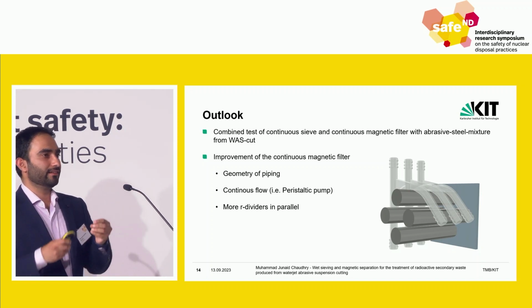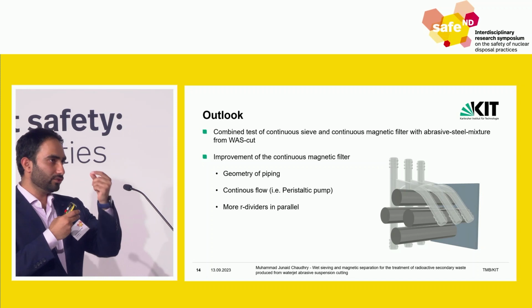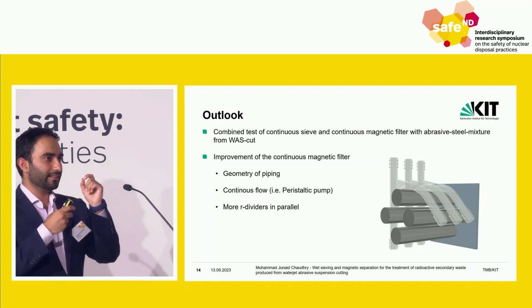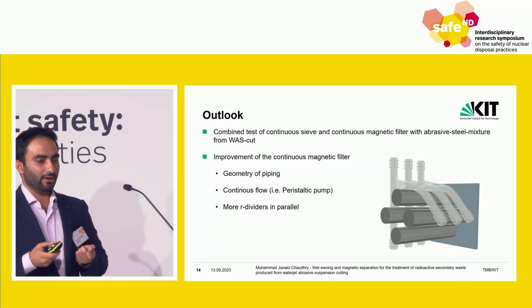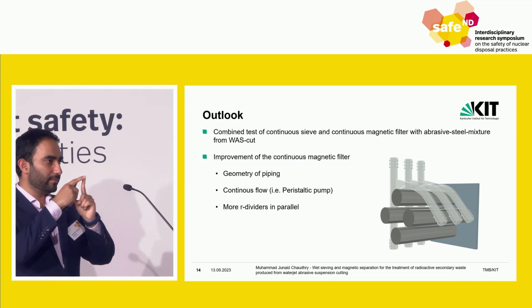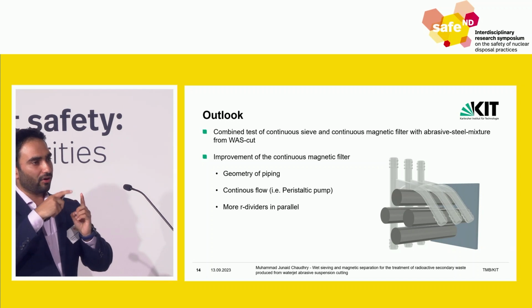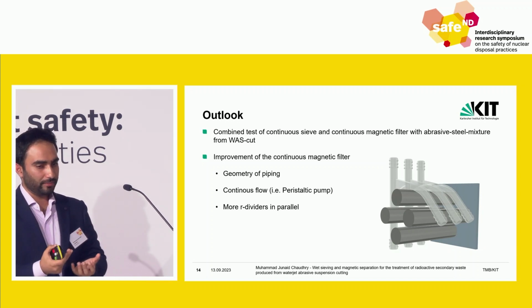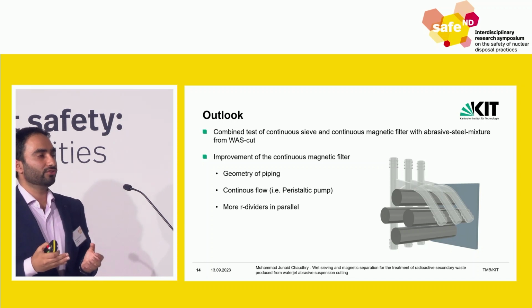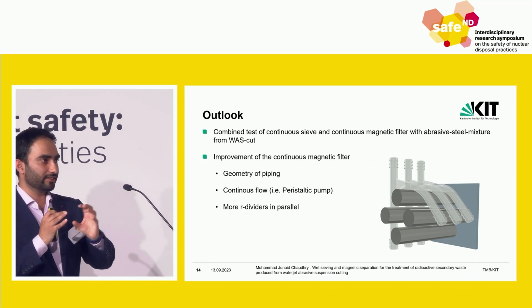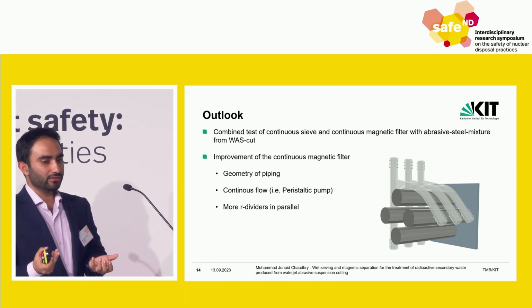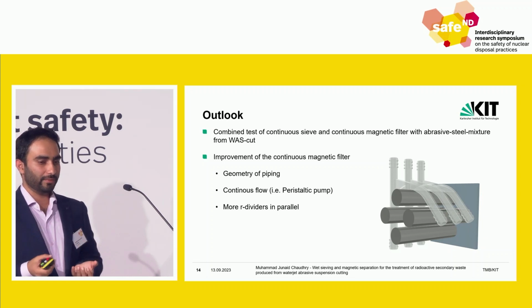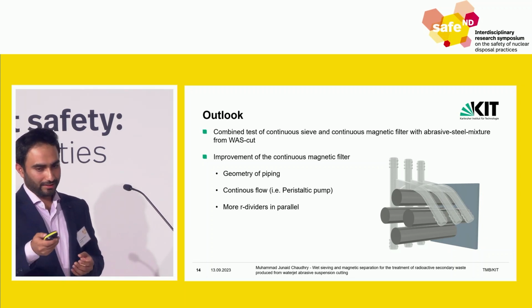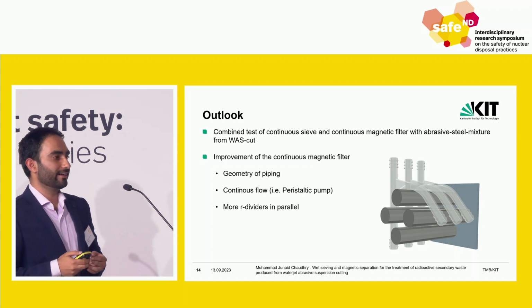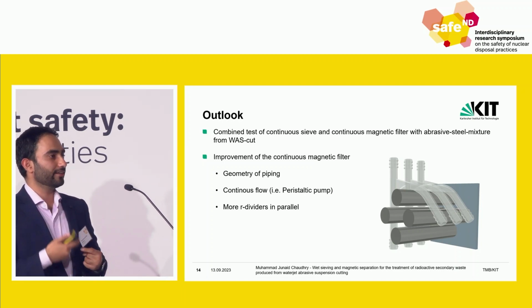For example, we can look for the material used for this rod divider, maybe the thinning of the walls, and also creating some kind of bump so the contact between the magnetic rods and the suspension would be much better. Similarly, right now we are using membrane pumps, which cause some pulsation that sometimes loses material, so maybe we'll use peristaltic pumps instead. As shown in the figure, we also want to use more rod dividers in parallel and see how the results are.